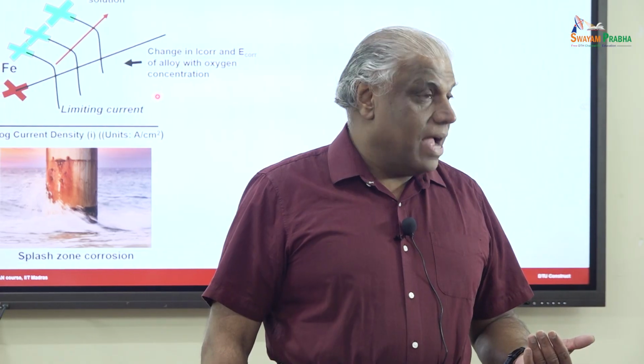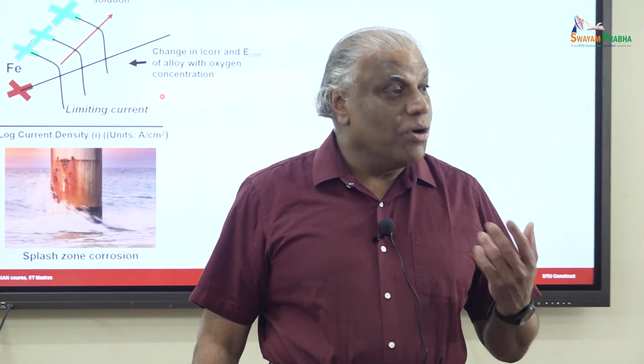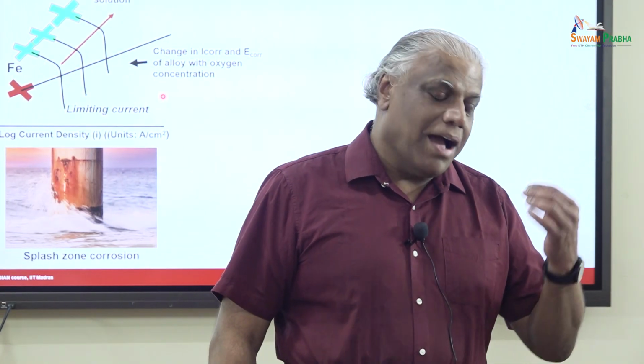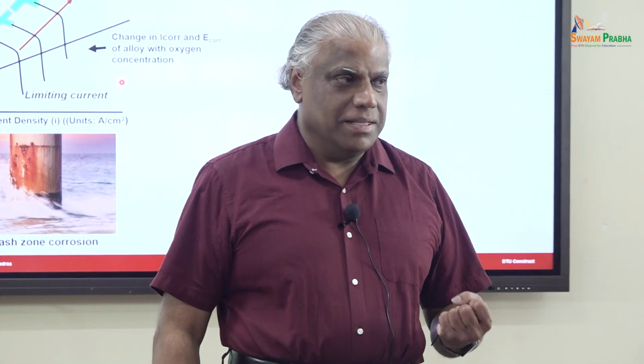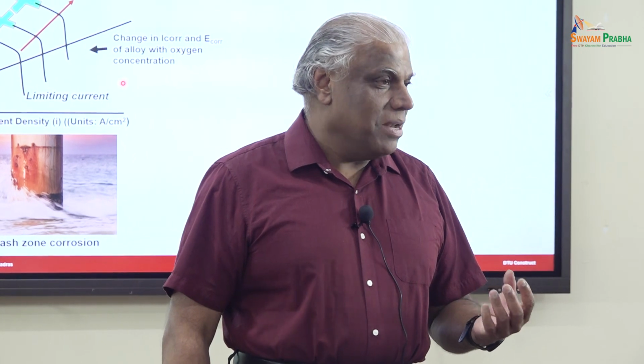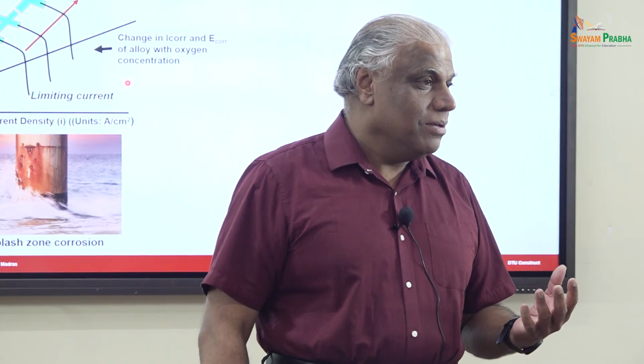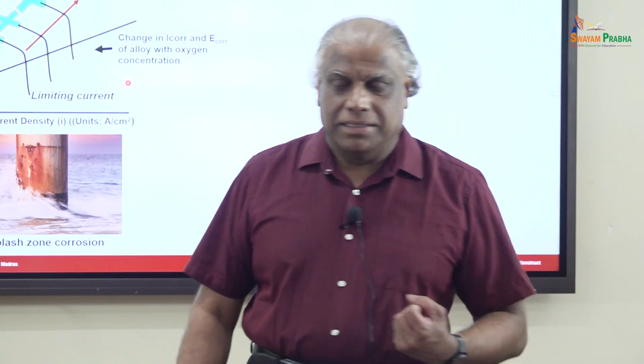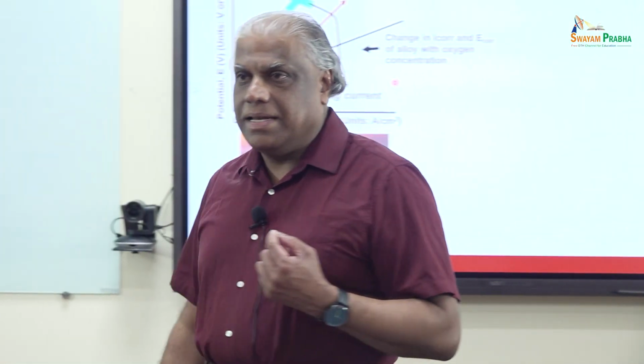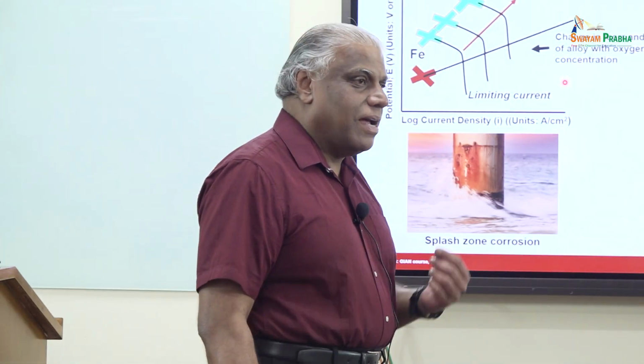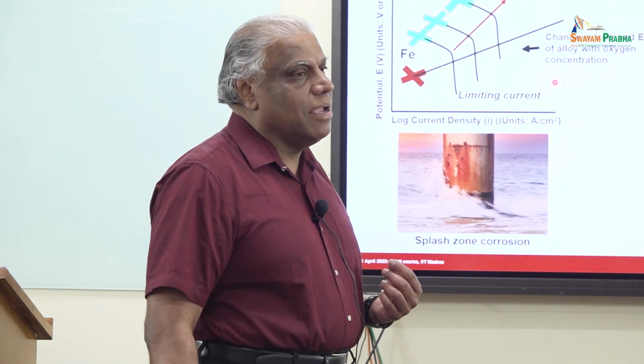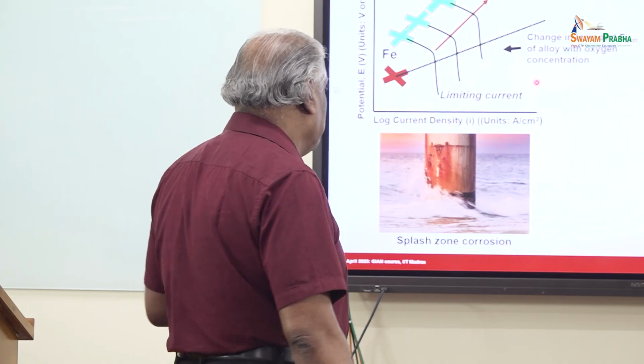This will not happen with hydrogen, because hydrogen is a small molecule, a small ion. Two things are there. One is that when hydrogen is present in the solution as ions, we don't call it diffusion anymore. It's a migration, because the field also affects because of the charge. And it's a small thing, so it can move faster. So hydrogen ions will not suffer from this limiting reaction.